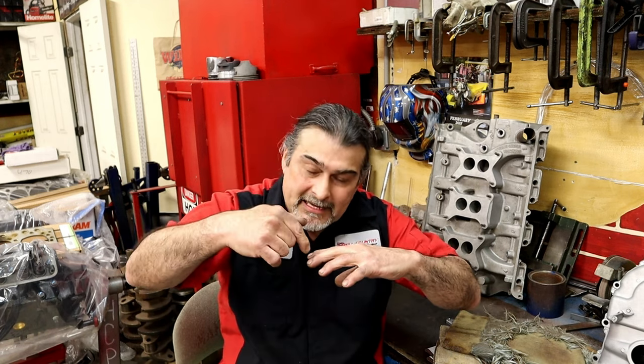Generally, if it's electrolysis from the inside or corrosion, the outside has one little pinhole and the inside could be the size of a quarter or a 50 cent piece. It's all eaten up and you got one little pinhole on top. Get that pinhole, V it out this way and see how big of a hole you got. Tip, if you got electrolysis or corrosion inside and you're welding one spot, that's not the only spot. That's the spot that went through. So tip of the day, think this through. You may be welding for days. I fixed this spot here, I pressure tested, it leaks over there. I fixed that spot, I pressure tested, it leaks over there.